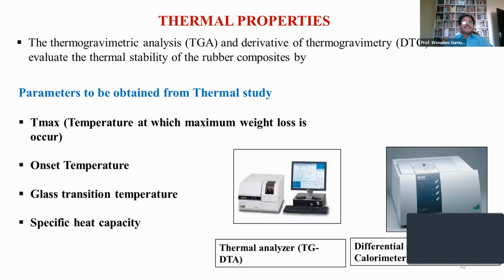Another important property is thermal properties. TGA is the method used to know the thermal stability of this rubber composite material, and some parameters we can calculate in this case. Some parameters like the temperature at which the maximum weight loss is taking place, onset temperature, glass transition temperature, specific heat capacity, and also different parameters are possible. The activation energy is obtained from the thermogram. Order of reaction can also be obtained from the thermogram by using some thermal methods. So this is the instrument shown, but what is thermal property and thermal stability? Up to what temperature is this material thermally stable? That is the stability temperature of the material, which can be known by using this TGA data.